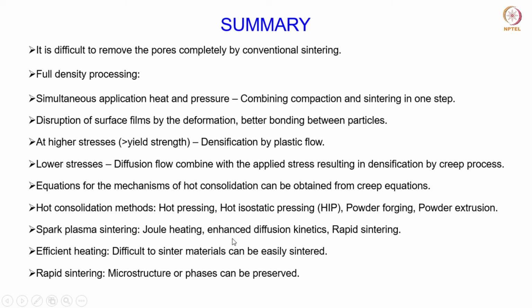Okay, so this results in enhanced diffusion kinetics, and as a result of that, a much rapid sintering compared to any other sintering process. Okay, and because of this enhanced densification, the process offers several advantages. For example, the efficient heating that you have in this technique will enable sintering of difficult to sinter materials. Okay, so there are certain materials which are difficult to sinter by other processes, but due to this enhanced diffusion kinetics and an efficient heating, the spark plasma sintering can easily sinter those materials as well.